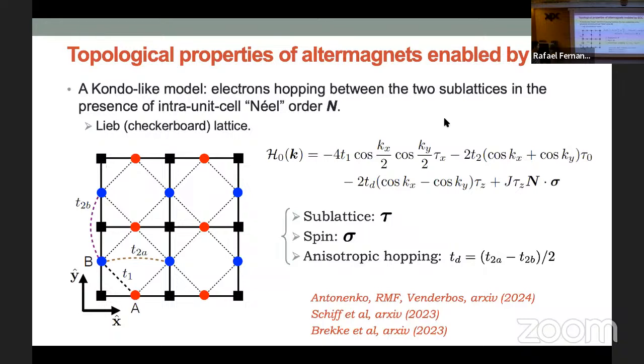So this here, if I have an antiferromagnetic order, is an altermagnet because my unit cell doesn't change, and I have to connect spin up and spin down by rotation. So in this Lieb lattice, I can write down my Hamiltonian, which has the non-interacting part of the electrons. And then I'm assuming, let's just do a simple Kondo-like model where I put the staggered magnetization, this N, coupling to the electrons that are hopping around. This is the simplest model you can think of. And the key quantity here is this hopping anisotropy. You see, the second nearest neighbors involving this sublattice along this direction is different from along this direction because here I don't see my non-magnetic atom.